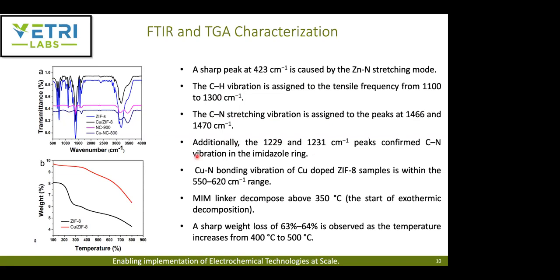Also, to confirm with the TGA, the TGA curve, as you can see, indicated a very low loss of less than 0.5 from 20 to 200 degrees Celsius. So this corresponds to the removal of the guest molecules from the cavities present in the MOFs. And we can see the methyl imidazole linker decomposes above 350 degrees Celsius, causing this weight loss. And you can see a sharp weight loss of about 63 to 64% for temperatures between 400 to 500 degrees Celsius on ZIF-8. And the final product would basically be zinc oxide on ZIF-8, and also on copper ZIF-8 it will be zinc oxide.